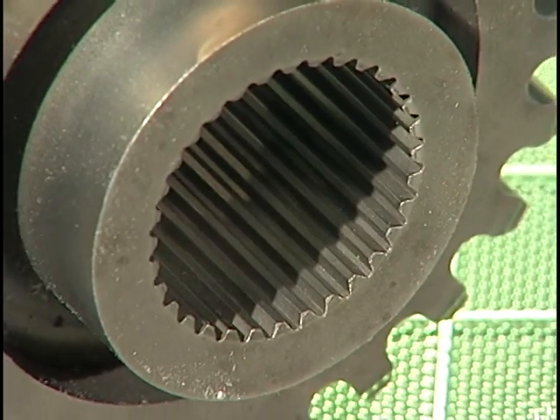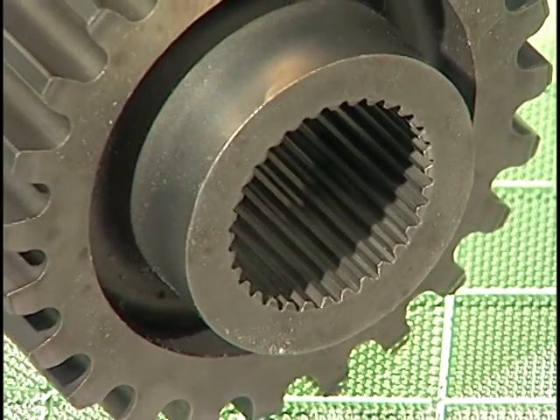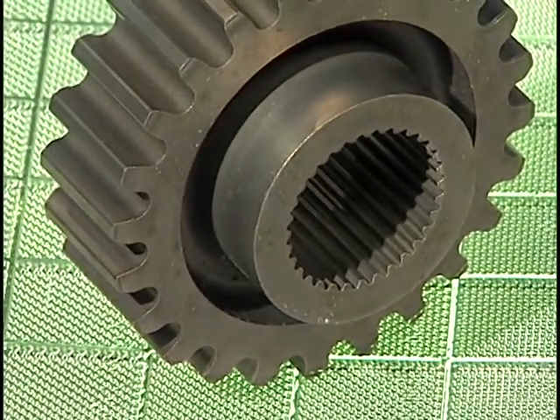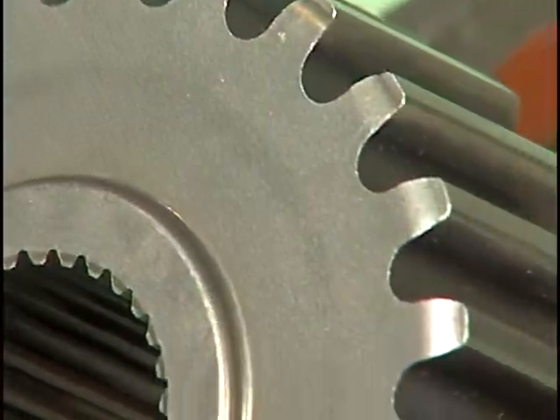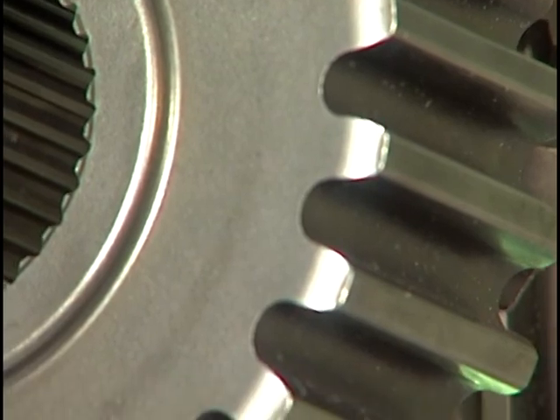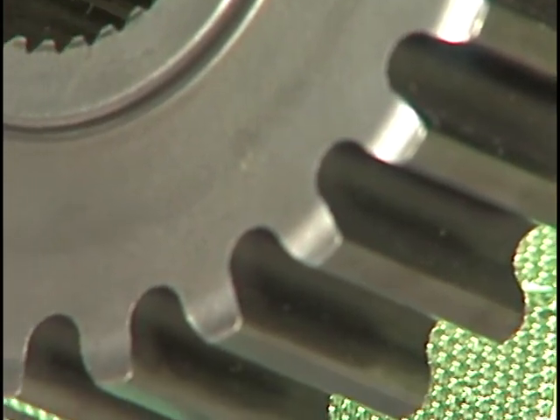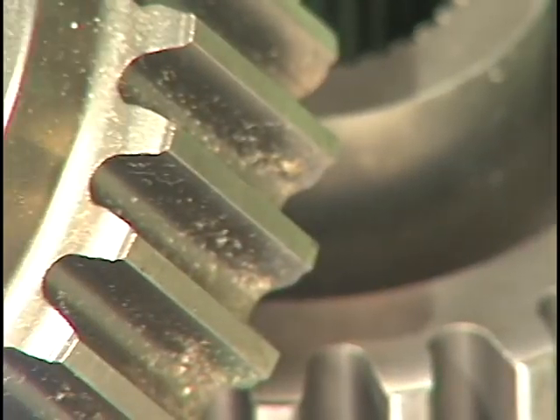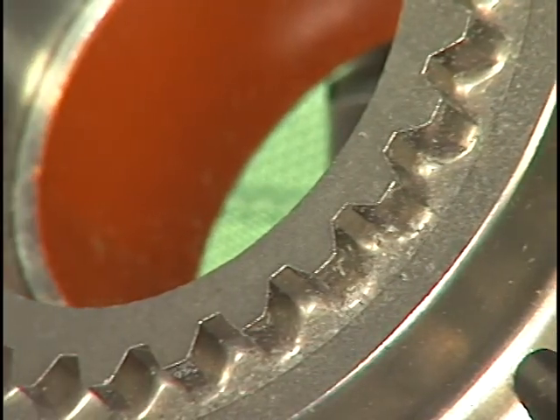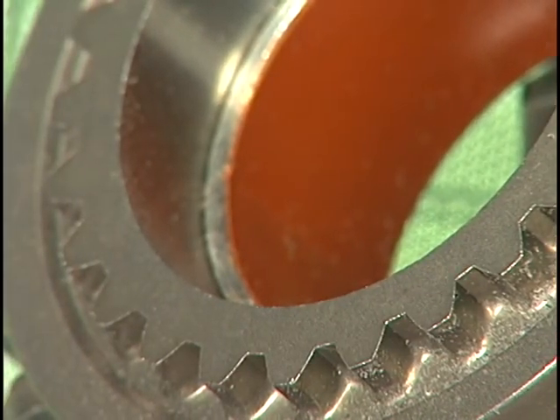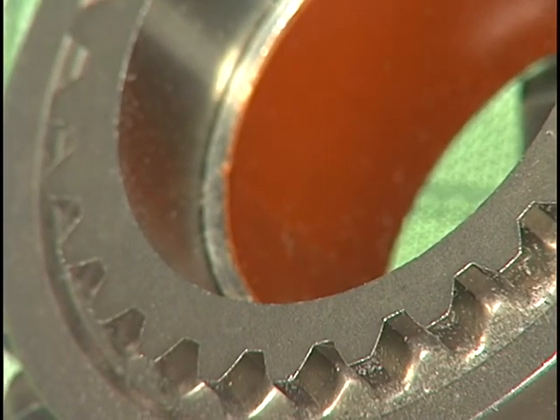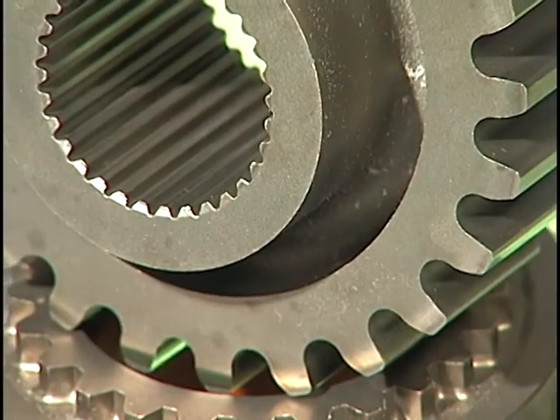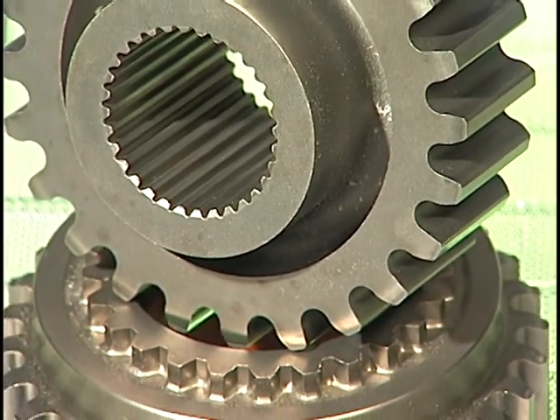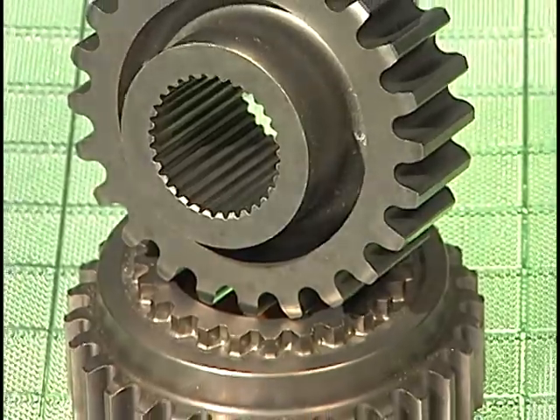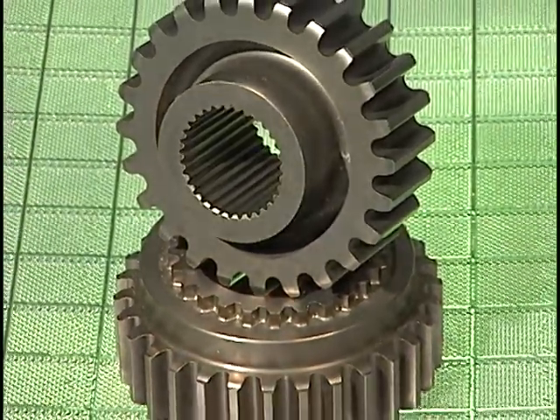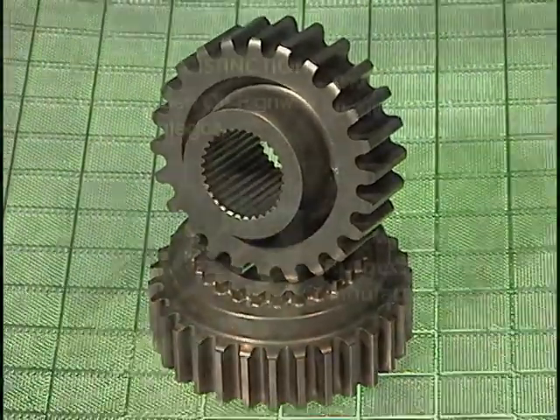Made from a modified MPIF FL4405PM material, the parts feature a density of 7.4 grams per cubic centimeter, a tensile strength exceeding 200,000 psi, an apparent hardness of 45 HRC, and a micro hardness of 60 HRC. The sprockets are carbonitrided for tooth wear resistance.